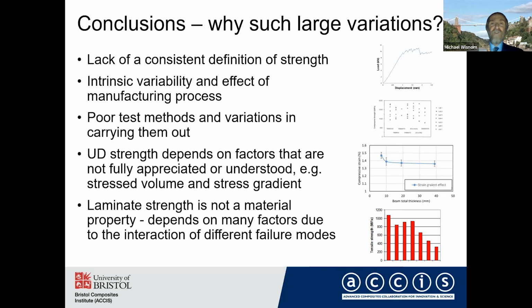So, in conclusion then, why do we see such a large variation in reported strengths? Part of it may be due to a lack of a consistent definition of strength. There's certainly intrinsic variability in effect of manufacturing processes. We have a lot of poor test methods and variations in how tests are carried out. But also, we have other factors, such as that UD strength depends on stress volume and the strain gradient. And laminate strength is really not a material property at all. It depends on many factors due to the interaction of different failure modes.